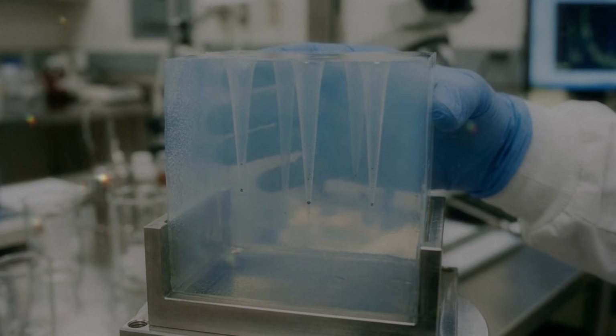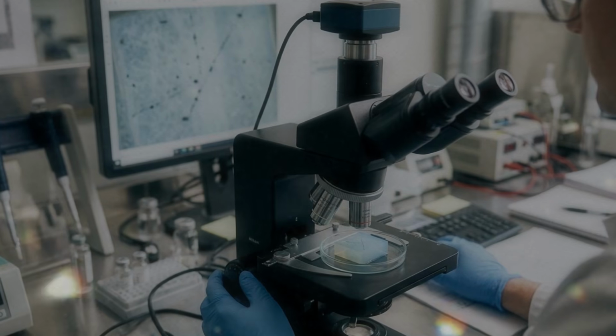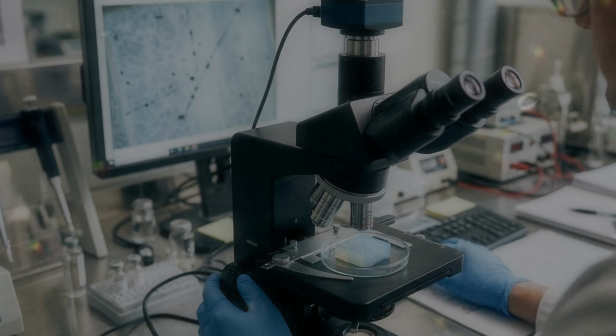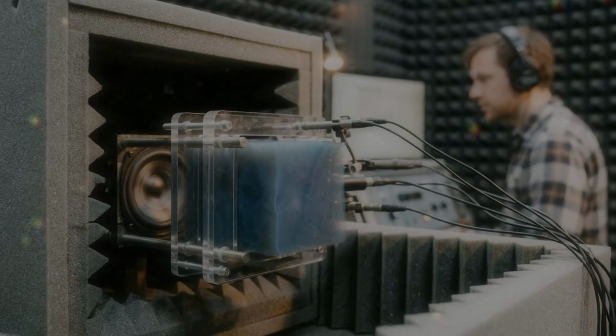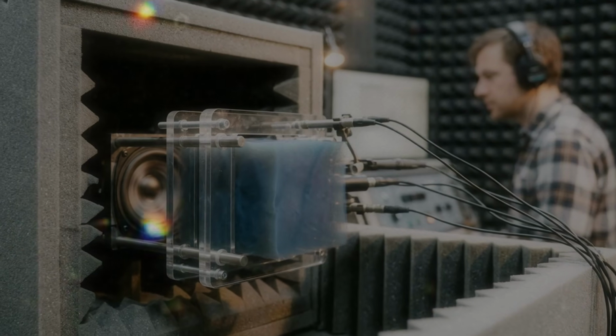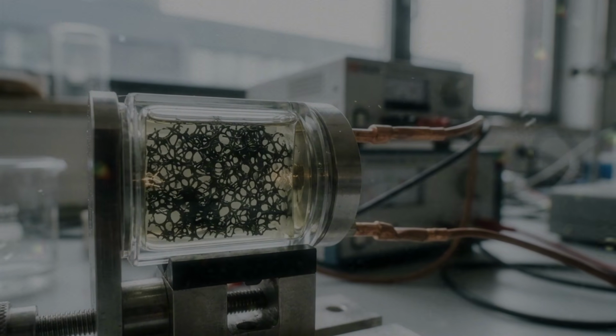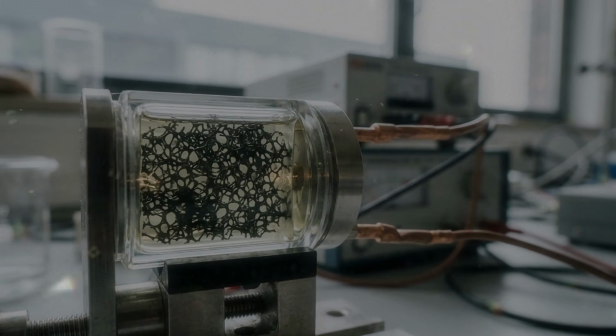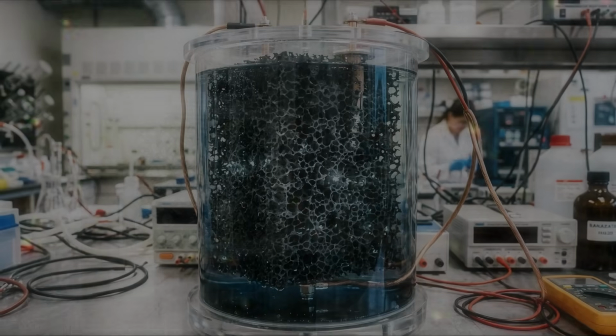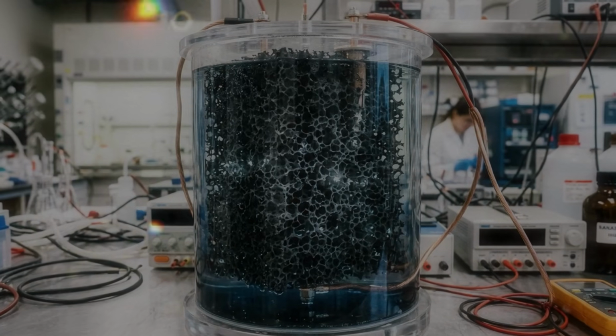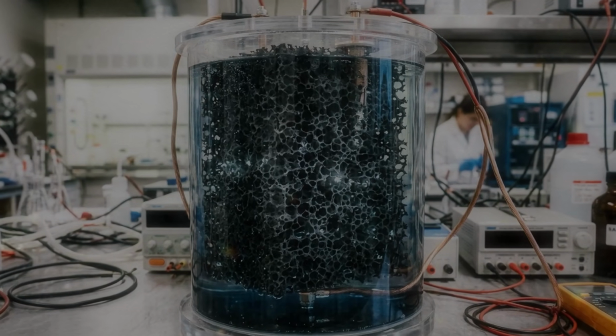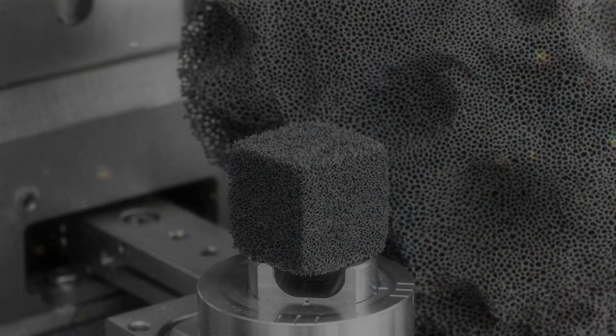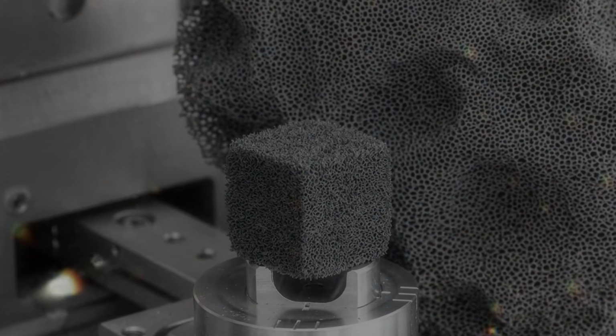The aerogel can act as a support, holding tiny catalyst particles apart and preventing them from gathering into larger clumps. This can reduce the amount of expensive material needed. Metals used in catalytic systems can be effective in very small quantities when they are distributed across a large internal surface. The same strategy appears in energy storage. An electrode works best when charged particles can reach a large active area and electrons can move through a connected conductive network. Graphene aerogel offers both possibilities.